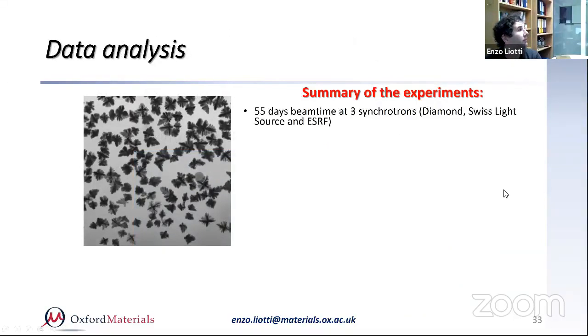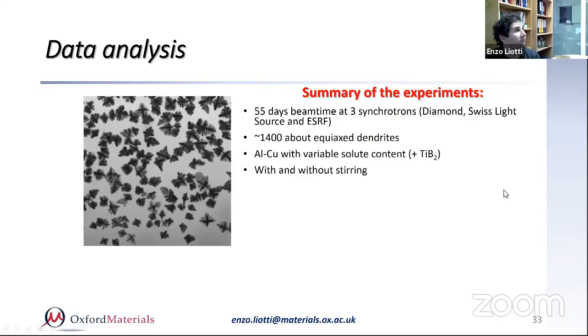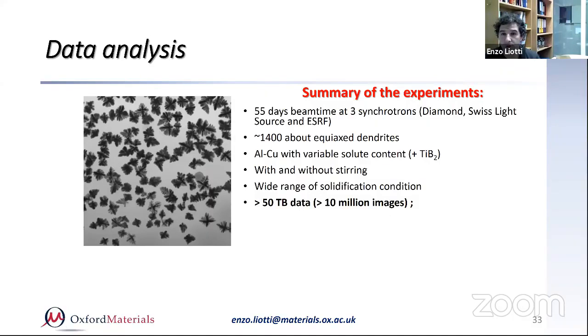Again, we've done many of these experiments. We spent 55 days at the synchrotron, using different synchrotrons here in Europe, in Switzerland, in the UK, and in France. And we managed to collect 1,400 experiments, all on aluminum copper with different solute content, with and without the grain refiner, with and without stirring. We cover a wide range of solidification conditions, in essence. That's accounting for more than 50 terabytes of data, which is more than 10 million images, right? Most of these experiments were of very good, high quality, like the image you see on the left.